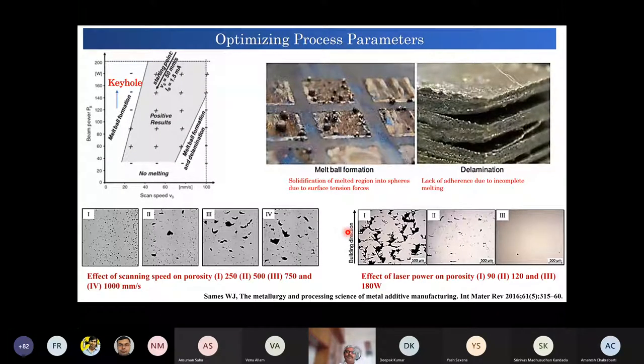Now I will just give you a very brief example which always attracts me as a metallurgist. There is a domain here, right? If we plot the scan speed versus beam power, there is a narrow domain where we get the best conditions of additive manufacturing and the most sound product. If we are on one side of it, there is a keyhole formation. What is a keyhole? I will show you in a minute. And on the other side, it is melt ball formation and delamination. So these are the melt ball formation and delamination kinds of defects that come in.